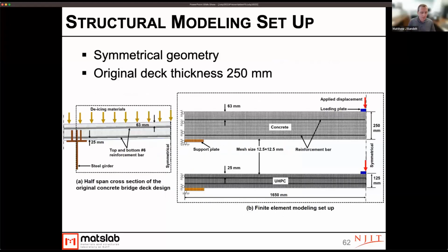So what we have here is basically a bridge deck. We're modeling a small portion of it. We apply some loads to it. And the main thing to note here is that for our concrete, we basically assumed a larger thickness than what we would have for a UHPC. Or I could say it the inverse way, in that if we were using one of these UHPC solutions, we might be able to take advantage of its high mechanical properties and use a smaller section thickness to result in equivalent strength. And so that's what we did. We designed these to have equivalent strengths. They'll wind up having different stiffnesses because you have different thicknesses, but the strengths were the same.